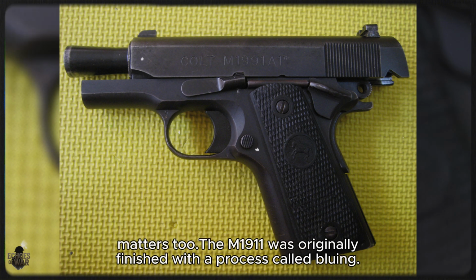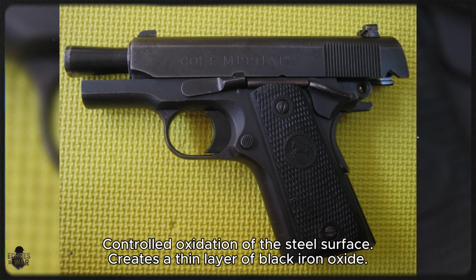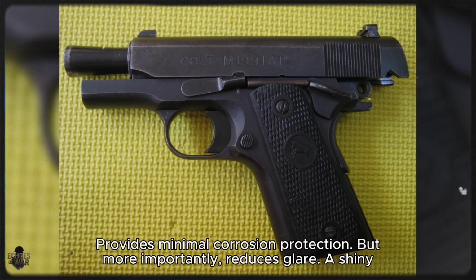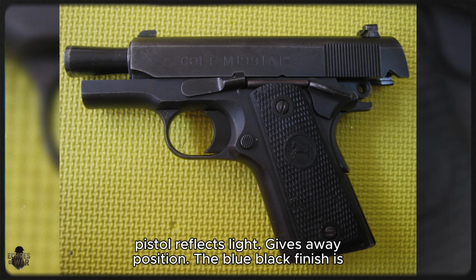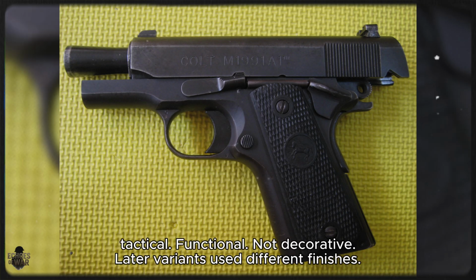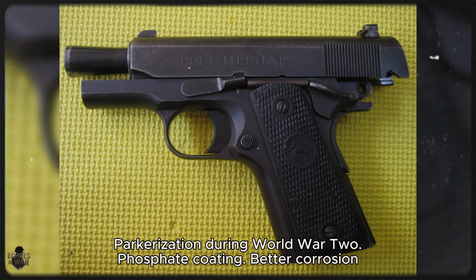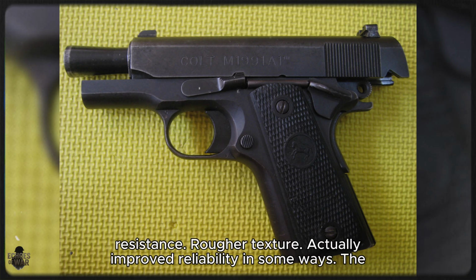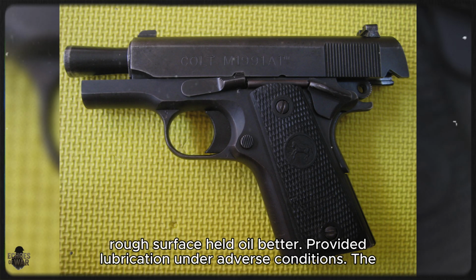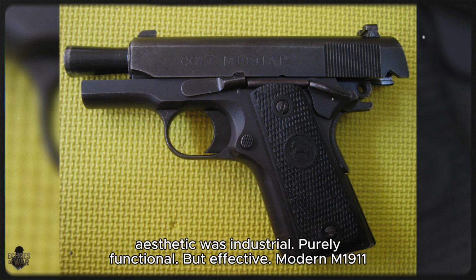The surface finish matters too. The M1911 was originally finished with a process called bluing. Controlled oxidation of the steel surface creates a thin layer of black iron oxide, provides minimal corrosion protection, but more importantly, reduces glare. A shiny pistol reflects light, gives away position. The blue-black finish is tactical, functional, not decorative. Later variants use different finishes: Parkerization during World War II, phosphate coating, better corrosion resistance, rougher texture, actually improved reliability in some ways. The rough surface held oil better, provided lubrication under adverse conditions. The aesthetic was industrial, purely functional, but effective.